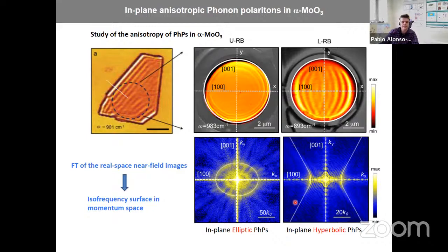It's quite peculiar, right? There are some directions where they cannot propagate, some others where they can propagate, but in these others where they can propagate, they propagate with different modulus of k, right? They have different sizes of vectors here, and all along all these directions. And particularly at the asymptote, you can have an infinite number of k's. And this is like an infinite number of optical states. For light-matter interaction, this is very important because you have many available k's where the matter can absorb the light and so on.